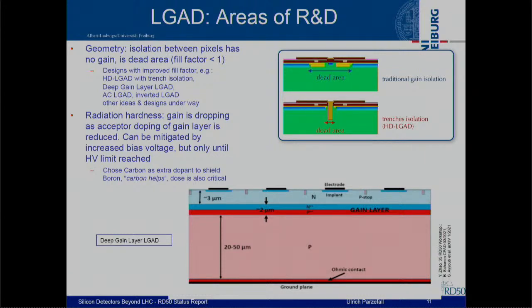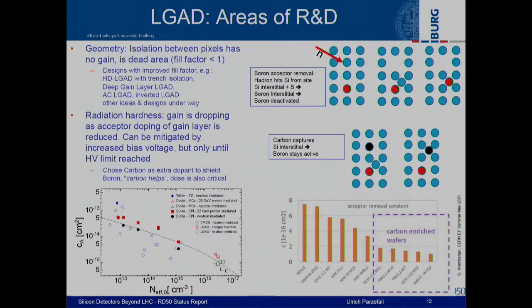Another area of concern and R&D on LGADs is radiation hardness. As mentioned earlier, doping changes as radiation occurs, in particular acceptors are removed, and you can see that the gain layer in LGADs is reduced as you irradiate. Here's acceptor concentration as a function of radiation dose, and the trend is clear that across all these materials acceptors are reduced.